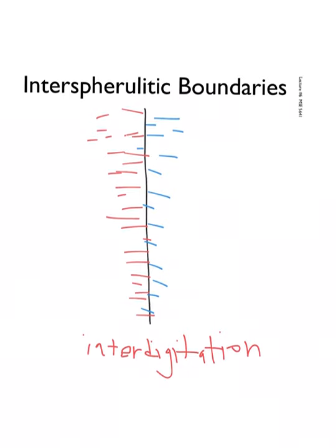So we have that crystalline component, which pays no attention to what the guy at the microscope is seeing. They don't stop just because there's an optical boundary there. Again, the optical boundary is an illusion. And then, of course, we also have the fact that the polymer chains were there first, and they don't pay any attention because they were there first. So the whole process of nucleation and growth doesn't change the fact that it's occurring inside polymers. And so you can have multiple polymer chains that are going back and forth across these interfaces and mixing and doing whatever it was they did before crystallization ever happened in the first place. Okay? Very, very different from a grain boundary.